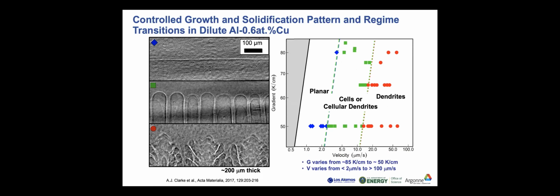So this is an example from a dilute aluminum copper alloy. So here we have 3 different snapshots from different synchrotron X-ray imaging movies. Up on top, we have a planar solid liquid interface. In the middle, we have these scalloped kinds of structures. And then down below, we have these hierarchical dendritic types of structures. And over here on the right, we have G versus V, and basically in real time, we're mapping out these different morphology regions and these growth regime transitions as well.